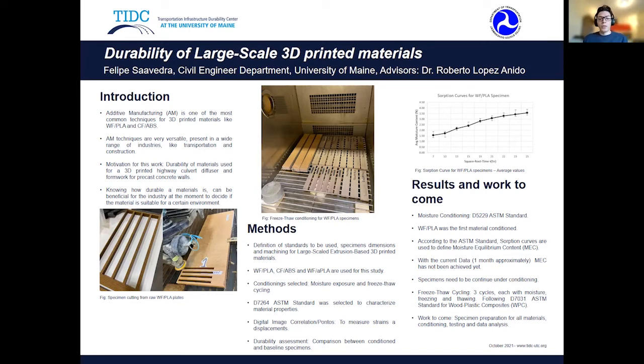According to the ASTM standards, sorption curves are used to define moisture equilibrium content. If you look at the figure above, sorption curves are the square root of time versus the average moisture content. For this set of wood flour PLA, it's not possible to say that moisture equilibrium content has been achieved because the curve has not flattened yet. This means that the material needs to continue under moisture conditioning to later be able to achieve moisture equilibrium content.